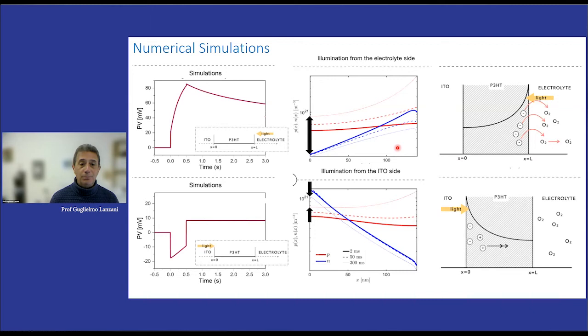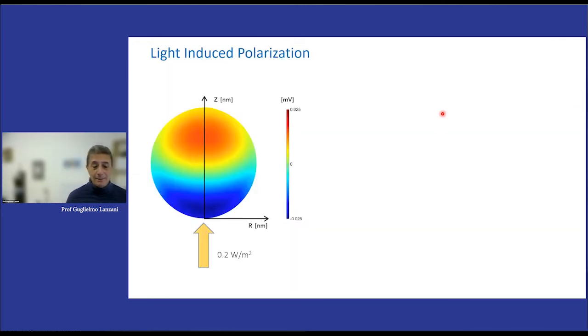Here you see the distribution of the charges. Blue is negative, red is positive. And you see also why in a thin sample, there is enough time for the far away interface to become dominant, while in a thick sample, this cannot occur when we shine light from the ITO side. When we shine light from the electrolyte side, we are in this situation, and of course the negative charge here is predominant, so it will be negative here and positive here, which is what we see in the simulation. So this model reproduced very well what is going on in the film, and now we did the 2D simulation, which of course is mathematically more challenging. And this 2D simulation again is reproducing the same polarization effect due to the asymmetric transfer.